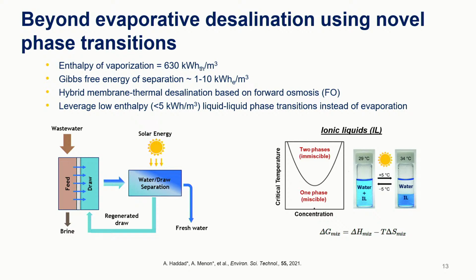And so looking at the mixing enthalpy, these ionic liquid water mixtures exhibit a negative entropy of mixing, and that's what really causes them to show this LCST phase behavior. So if we're able to hit the critical temperature, which as you can see here only needs to be a few degrees above ambient, the higher up you go, the better your separation, but typically around 60 to 70 degrees Celsius is that target upper temperature.